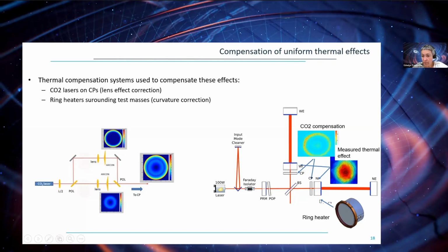And in order to compensate for the deformation of the surface, we also have installed ring heaters around these input test masses to correct for the radius of curvature. So it works reasonably well, with, of course, some limitations in the sense that you cannot perfectly correct, and that's why we are in any way still limited by these effects.